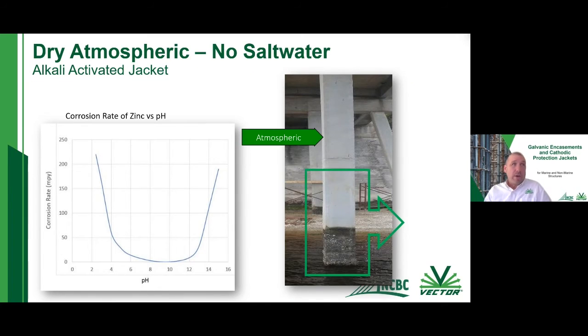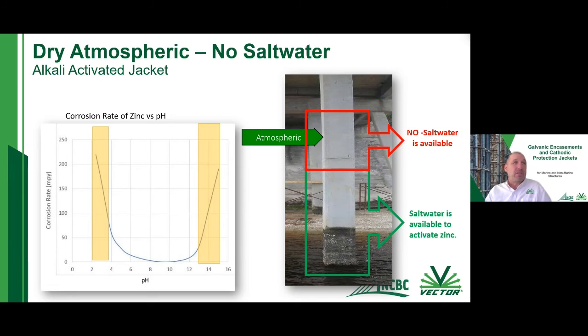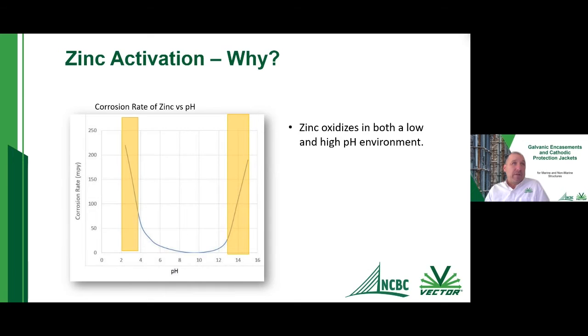And so what ends up happening is without that salt water, we're going to have to rely on something else besides the salt water that's in the environment. So this is that corrosion rate versus pH graph again as well. If we look at the corrosion rate of zinc on here, we can see that zinc corrodes either in a low pH environment or in a high pH environment. So we're going to obviously want to use a high pH environment for it, right?